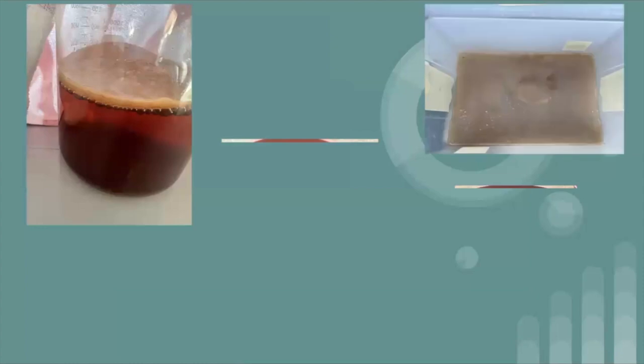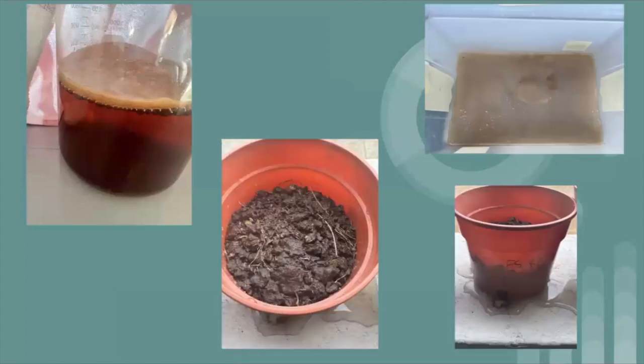Now, how did we create this? How did I create this during my research? Well, first of all, I'll talk to you about the fermentation process. The fermentation process of bacterial cellulose includes three ways: static, agitated, or stirred conditions. A three-dimensional linked reticular pellicle was seen in the static state. However, irregularly shaped sphere-like cellulose particles were generated in both stirred and agitated conditions.